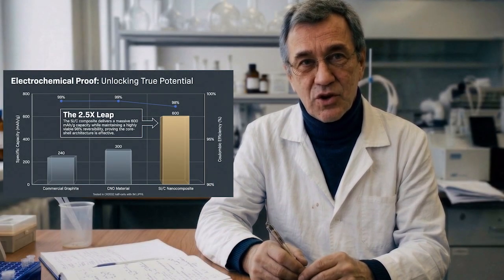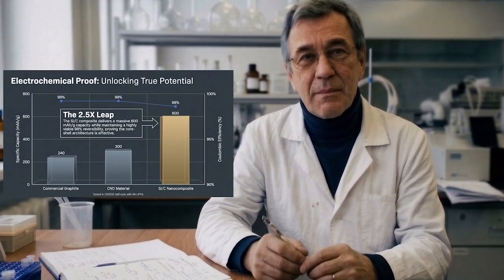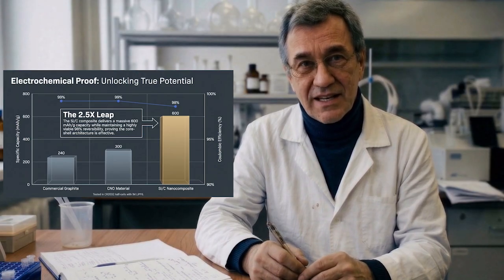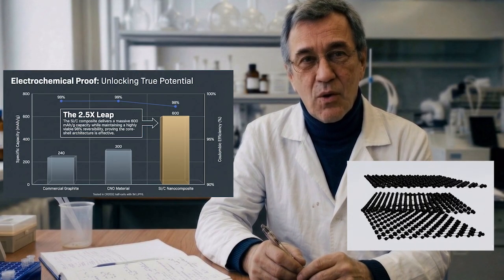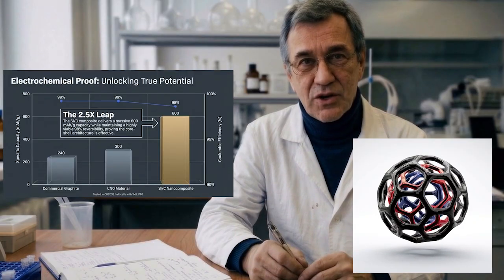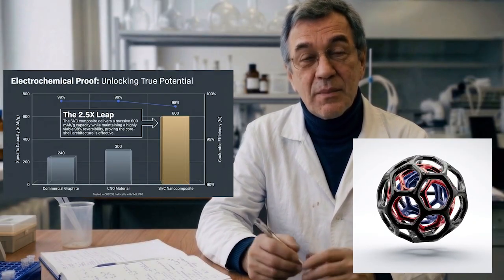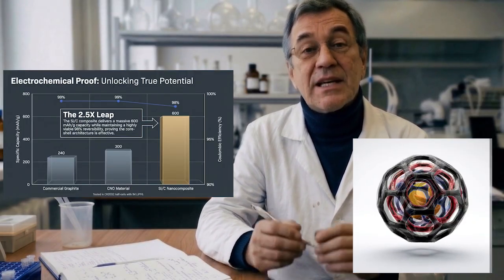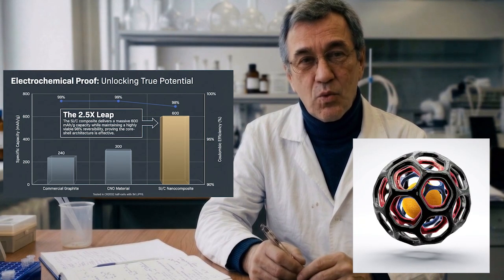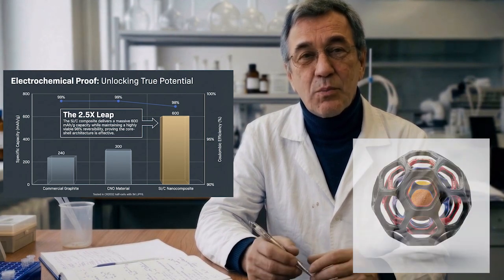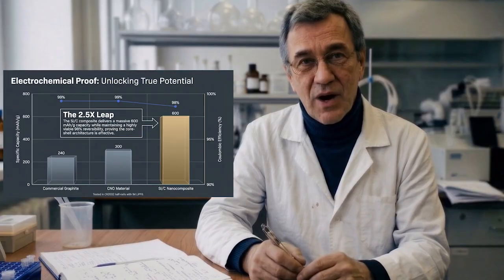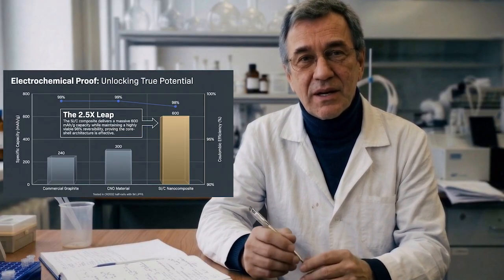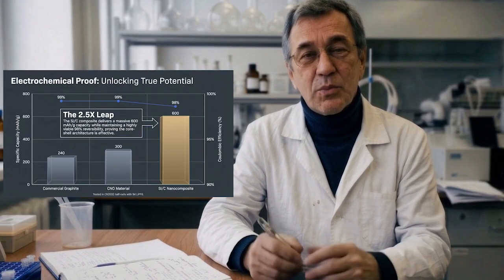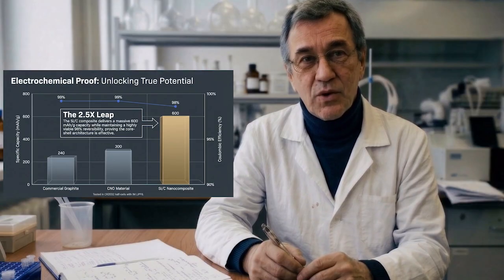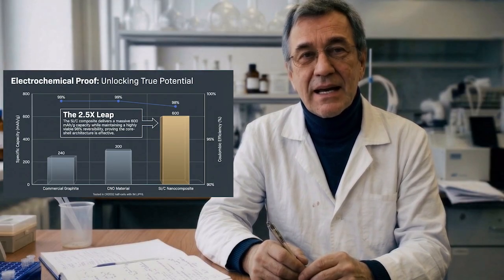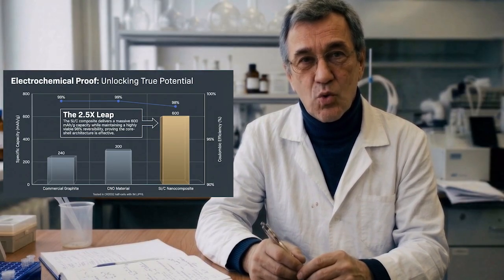Let's look at the key results. First, the maximum specific capacity. As expected, graphite topped out at 240 milliampere-hours per gram. Our CNO material gave a healthy boost to 300 milliampere-hours per gram. But the silicon-carbon nanocomposite delivered a remarkable 600 milliampere-hours per gram, more than double that of graphite. In terms of coulombic efficiency, all materials performed exceptionally well, hovering around 99%, indicating highly reversible lithium storage.